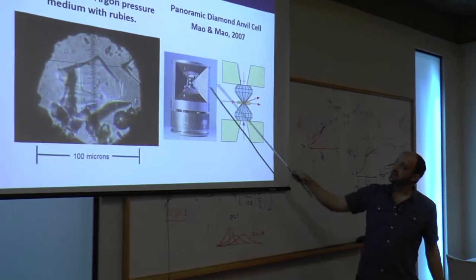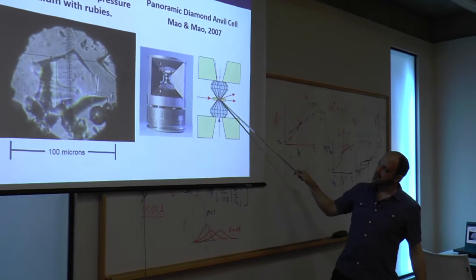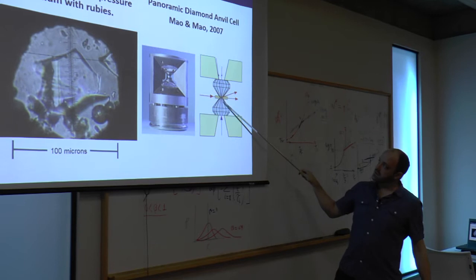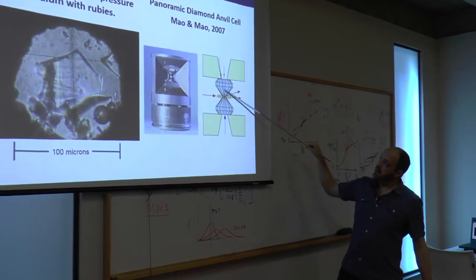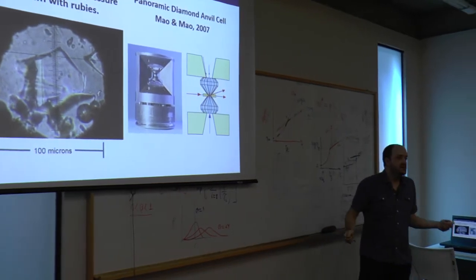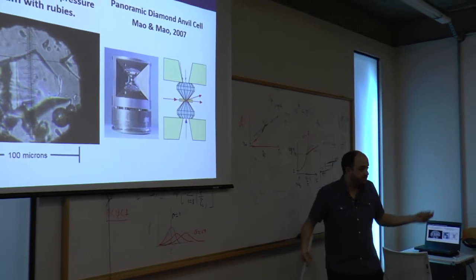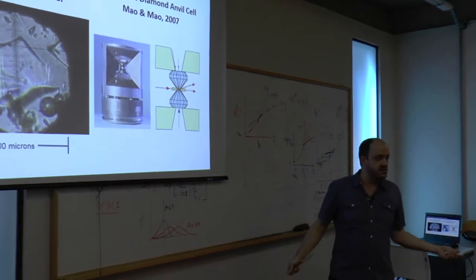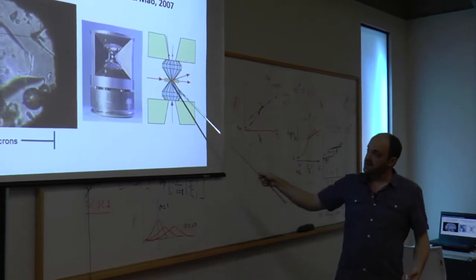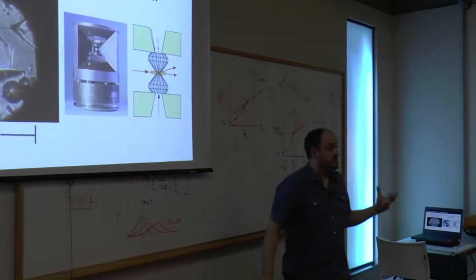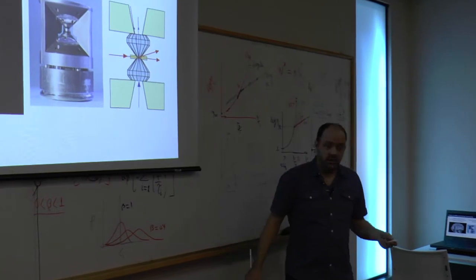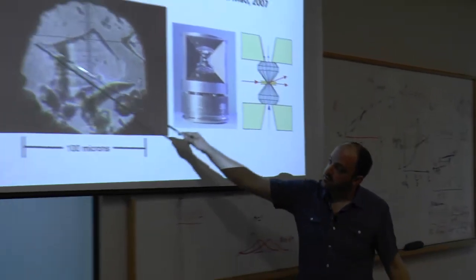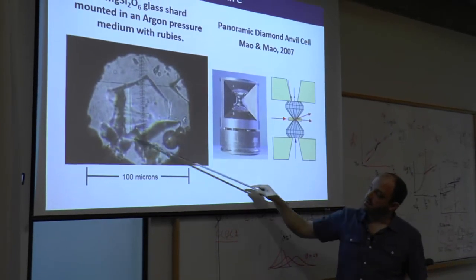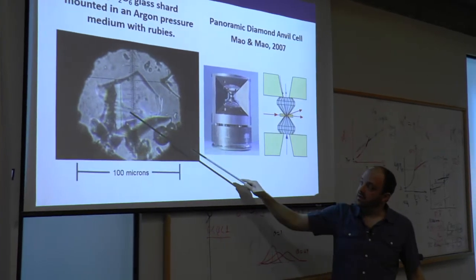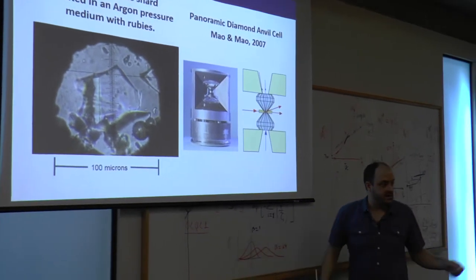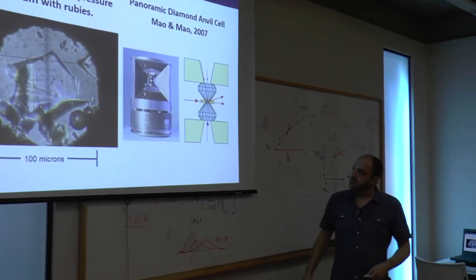So this sample is sitting in between 2 diamonds and held in there by this gasket. And because diamonds are transparent, we can see through and use the diamond as a window to get to the sample. Since we're using our green laser light, it's no problem to get onto the sample and back out. And we showed our spatial resolution of a couple microns. So it's no problem. This is a 100 micron hole. This sample is probably about 50 microns. It's no problem to get half a dozen different analyses or even more on the sample.